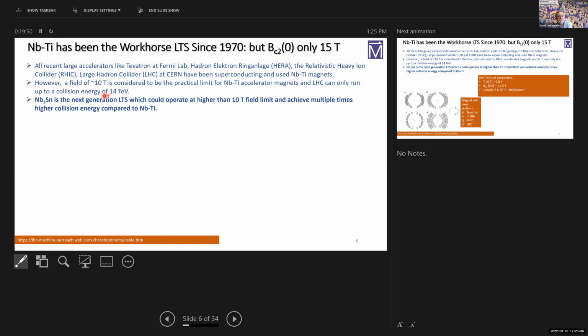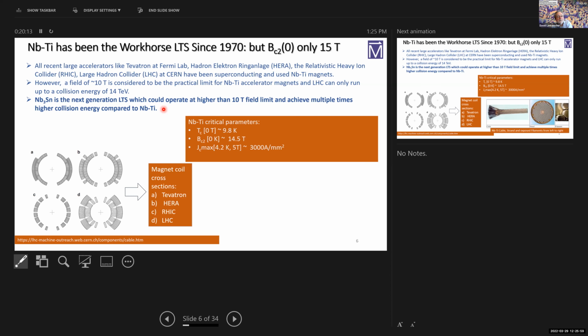But in fact, niobium tin is that next generation LTS. And the high luminosity upgrade of the Large Hadron Collider is using niobium tin magnets in the intersection regions, quadrupole magnets, to squeeze the beam to get the intensity up much higher. And so these are kind of dipoles. These are cross sections, starting with the Tevatron in the very early 1970s, HERA in Germany, RHIC at Brookhaven, and the Large Hadron Collider.